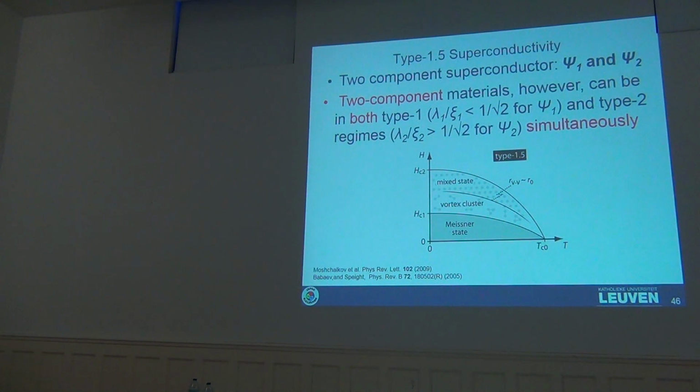So this reminds you of the following situation. If you take type 1 superconductor in an intermediate state, then you have stripes of superconducting areas, normal areas, superconducting, normal, superconducting, normal. And then you deposit on top of that a type 2 superconductor. Then in the area where vortices penetrate, on top of the type 2 superconducting film you will see a lot of vortices. Here you will see none. A lot of vortices and none. So that's why you may expect these stripes to appear.